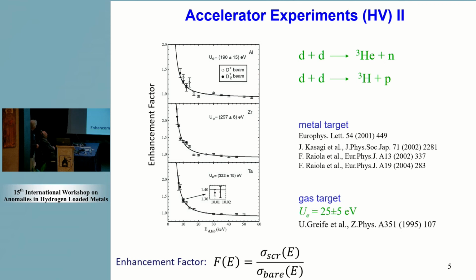And you see here an enhancement factor. So we compare reaction rates to the theoretical ones without any electrons, because DD reactions are known very, very well. The cross sections are known, studied many times in the last 50 years. And therefore we can calculate this enhancement factor as a ratio between the experimental cross-section we measure and the theoretical one that is determined for bare nuclei without any electrons. And what you see is that for different targets, where the deuterons are implanted in metallic targets, we can see that the cross-section in these different environments increases differently.